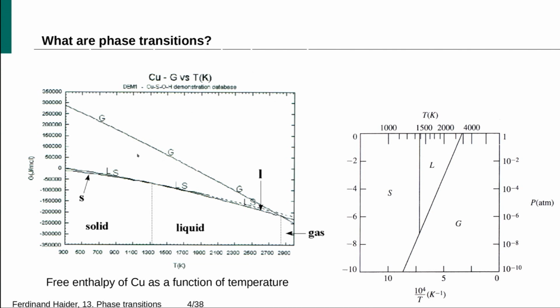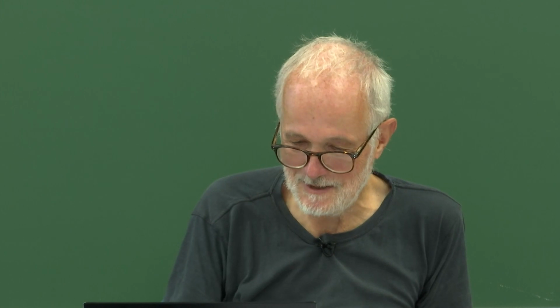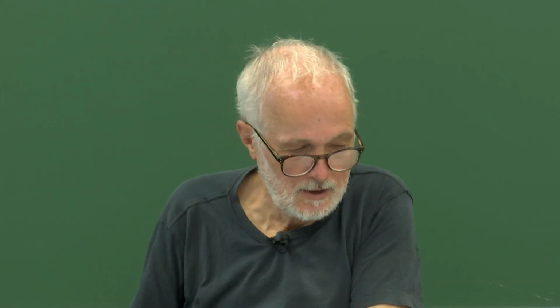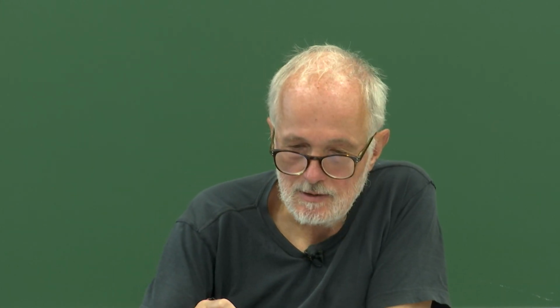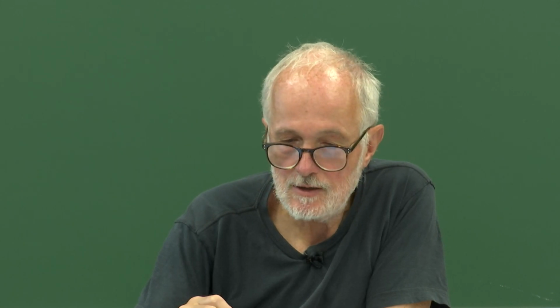It's much better visible for the gas phase, because the difference in entropy between the gas phase and both the liquid and solid phase is much more pronounced than the difference between liquid and solid phase. I found it interesting - intuitively, one would assume the entropy of the liquid phase is far higher than that of the solid phase, but it seems not to be the case. So we can say a bit more about this - let me repeat this little sketch here.